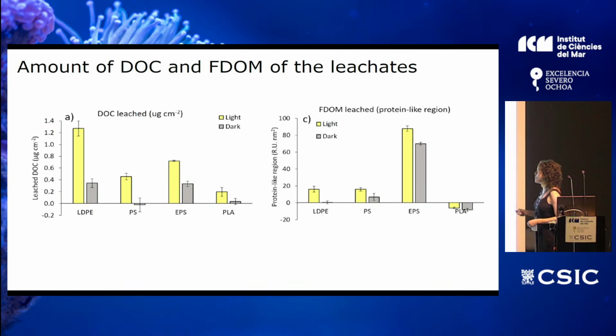So here also we have the amount of DOC and fluorescent DOM from the leachate of these four plastic types that I showed you before. So this is the amount of DOC leachate in the light and dark. We have here that the LDPE, the low density polyethylene, was the one releasing the most DOC, followed by the EPS. And then in all of them, the irradiated was higher than the dark one. And interestingly, the biodegradable plastic released less DOC than the rest of the plastics. So we already know that this plastic was not biodegradable in the conditions of the ocean, but I would expect maybe more leaching than the others, but it wasn't.